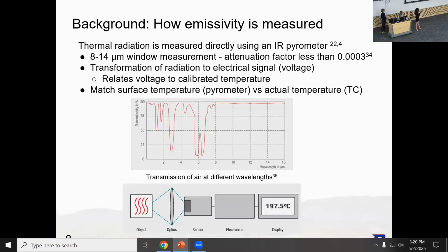Additionally, a pyrometer works by having your object radiating emission, and the optics pick it up and the sensor transforms it into an electrical signal, which is calibrated in the pyrometer to be a set temperature. With that temperature, we're able to see the surface emission temperature being radiated. In our setup, we have an implanted thermocouple, which Noah will get into in a second, inside of our sample to see the total temperature that has been absorbed. If you can see how much temperature is absorbed and how much is emitted, you can see the difference between the two, and the pyrometer can calculate your emissivity value.